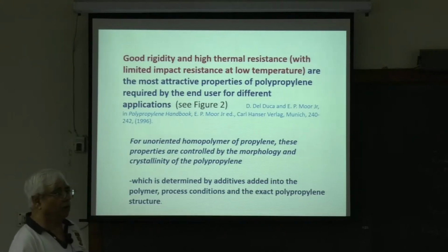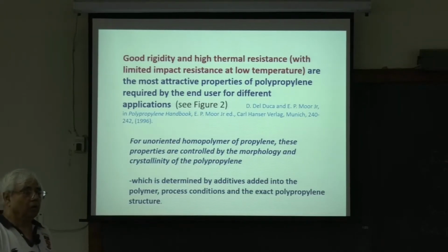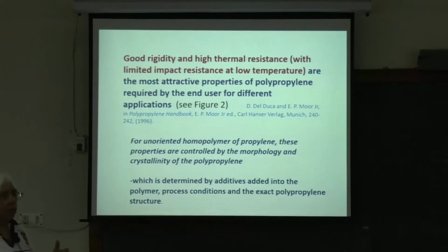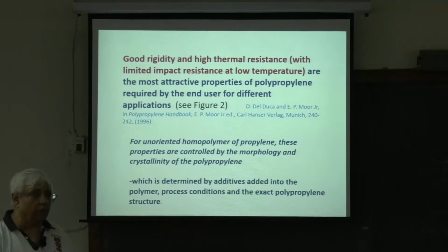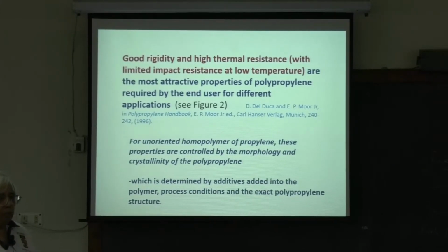But when CIPET Director General Dr. Sanjay Naik came to our university with his team, he saw, as I will show in a future presentation, that using fly ash and polypropylene had in fact improved the impact fracture strength by about 50%. He was very surprised. He said, Dr. Bandyopadhyay, we must take up this thing, because polypropylene is very prone to brittle impact fracture. And he said, if fly ash itself is brittle, can we put fly ash in? Then I said, yes, we can.